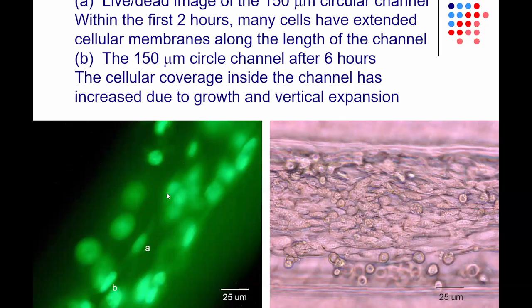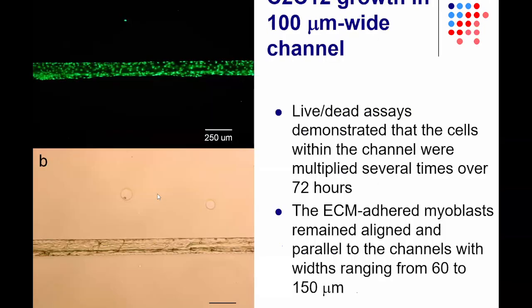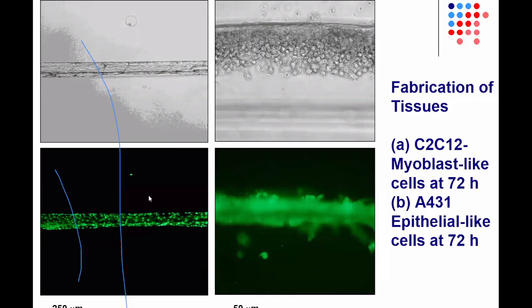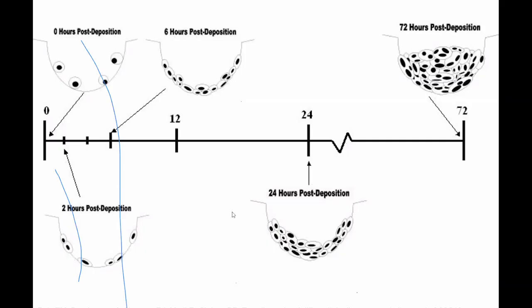Here you can see examples of cells grown in the surface. As we mentioned, we put cells in a reservoir and then flow them into these laser-cut channels. You can see here that you have good cell coverage. These are myoblast-like cells. You can see here that they will align and form parallel features from 60 to 150 micrometers in width. And you can see here epithelial-like cells, A431 cells, also able to proliferate within these channels.